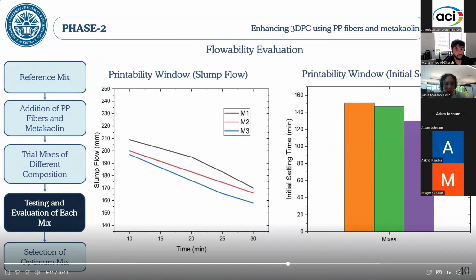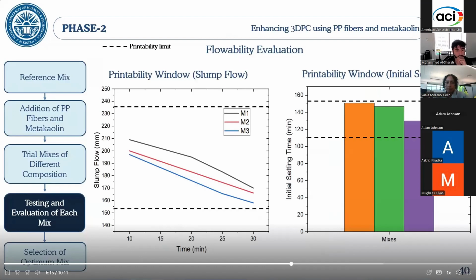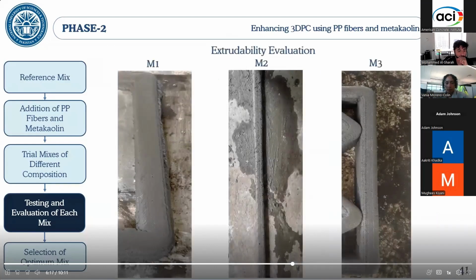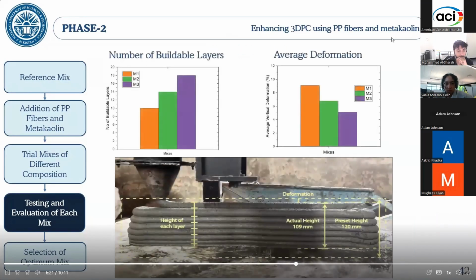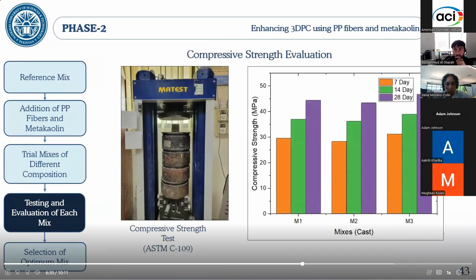Both M2 and M3 fell in the optimum flowability range, which we established while developing our base mix. M2 and M3 also passed extrudability criteria. All mixes had deformation below the limit stated in literature, so buildability wasn't an issue either. All 3 mixes also had adequate strength.